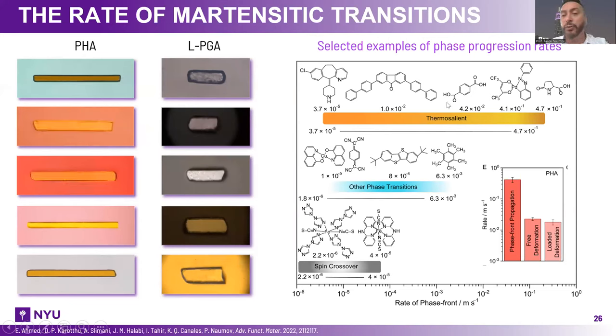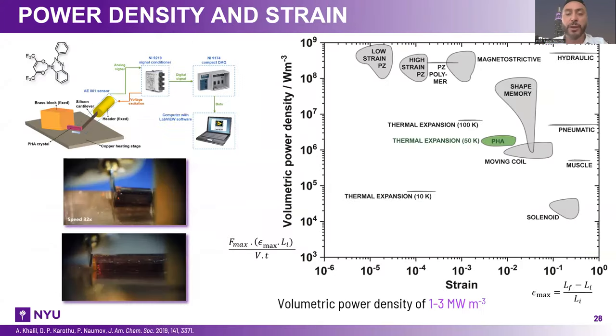But what is important is that we measured the phase front progression in these crystals, and we found that they are one of the fastest phase transitions, if not the fastest phase transition. So this puts us in a very special position to actually use phase transitions to actuate, to move other things around. And also we found that the phase transition progression front does not always correlate to the expansion of the crystal. There is some lagging there. And that comes from the fact that some of that kinetic energy, or elastic energy, dissipates before it's converted to kinetic energy to perform mechanical work. So I can answer more questions in relation to this in the follow-up session.